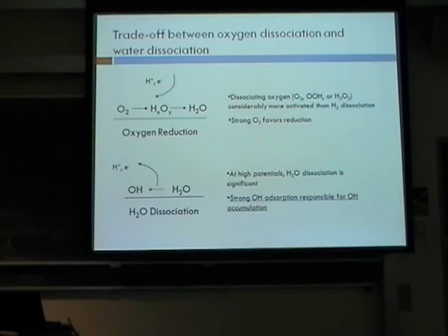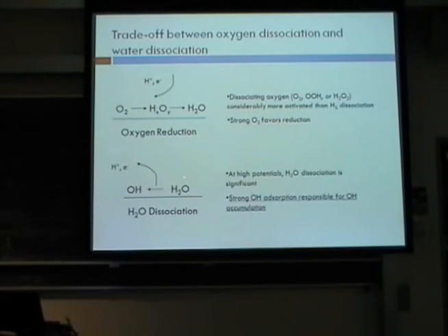Okay, I think we may have talked about a lot of this already. So one thing that's definitely observed is that atomic oxygen can be a problem. What's been seen in in situ spectroscopic studies is that it's really the hydroxyls that accumulate on the surface and choke off the reactivity. And so a lot of the effort has been devoted to finding ways to destabilize hydroxyls on the surface so that you favor them going on to form water.